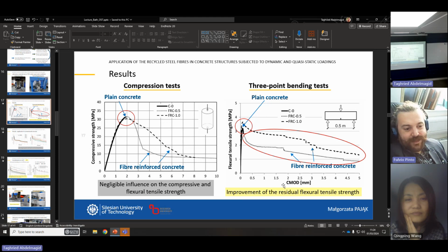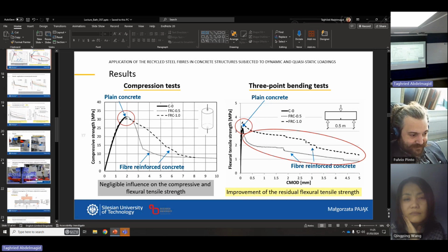I mean, you have an increase in energy absorbed here, which is massive. While it doesn't mean, in my opinion, that the structure can still be used, it gives the possibility to prevent any critical collapse, which is very good. Yes, and it can also be an alarm for doing repairs. So it makes sense to me. It is very interesting. Perhaps controlling the specific length of the reinforcing fibers may actually improve this even more, because an increase of 1% or 0.5% in weight is acceptable if it gives you this advantage.